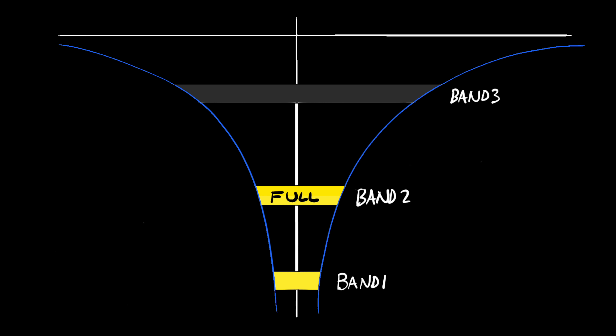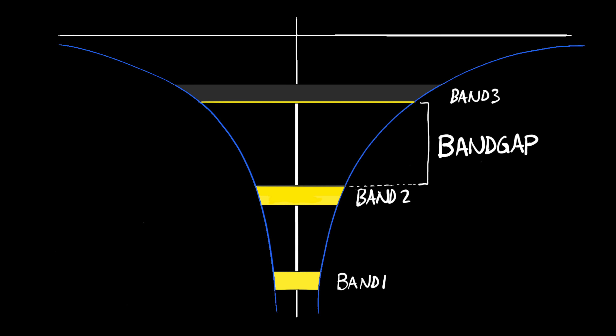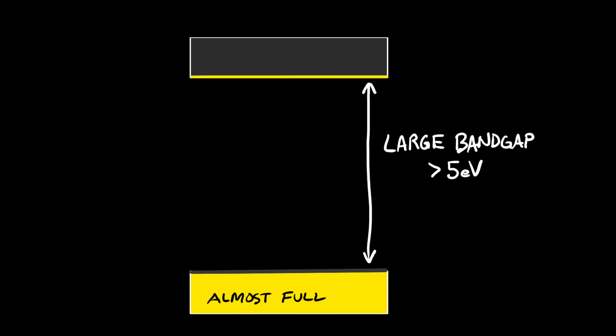This finally explains why metals like copper can conduct electricity without requiring ionization energy. What if the highest occupied energy band is totally full? In that case, any electrons in that band are stuck in place unless they receive enough energy to jump all the way up to the next band. The gap between the two energy bands is called — obviously enough — the band gap. In most materials, the band gap is large, so it takes a large amount of energy to move an electron to the next band; the electrons are stuck in place and the material does not conduct electricity. Any material with a large band gap is an insulator.